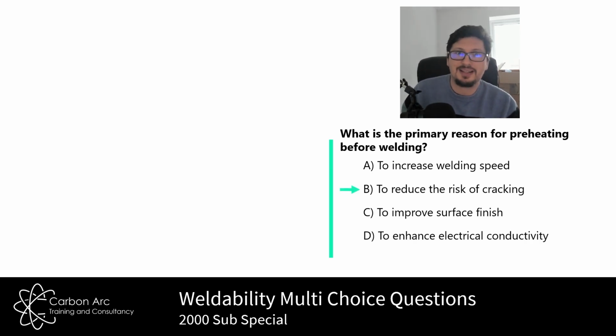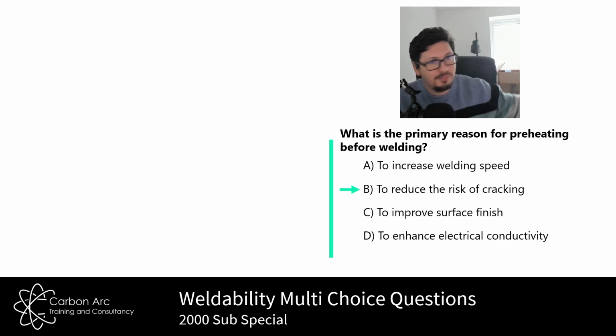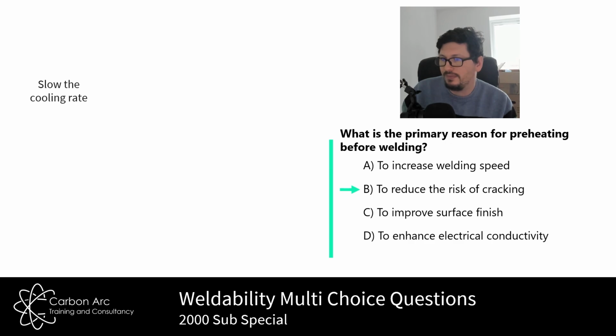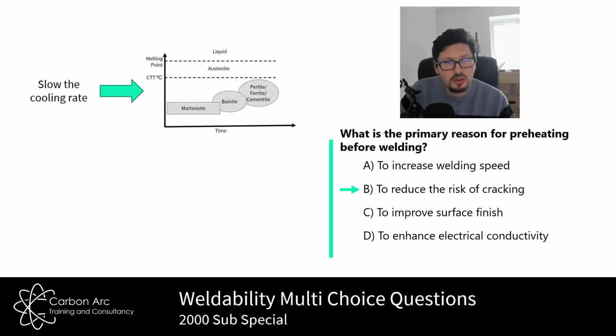Some materials, like a 690, you're going to need to have a high preheat and a very slow cooling rate. So you put a relatively high preheat in place, you try to weld it relatively hot, and when you finish, you cover it in fire blankets and you just let it cool over hours, maybe a couple of days, and then take the blankets off, and then hopefully it hasn't cracked. So again, slowing the cooling rate.